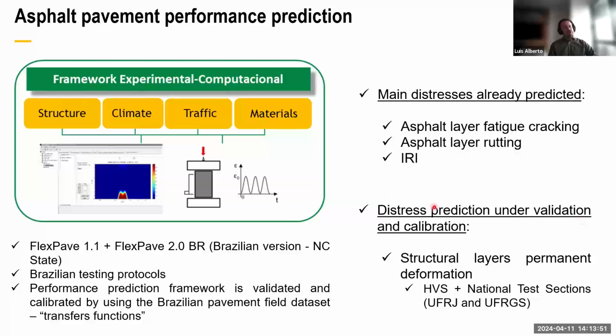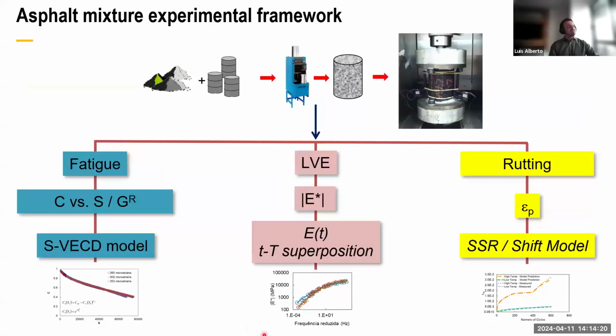In this case, we have a very special condition, because in order to calibrate the models for permanent deformation of the structural layers, we need to evaluate each layer's contribution to the permanent deformation individually. So that's why we have been using a heavy vehicle simulator to validate the models, and then later we calibrate the models using our national test sections. It's a two-step protocol.